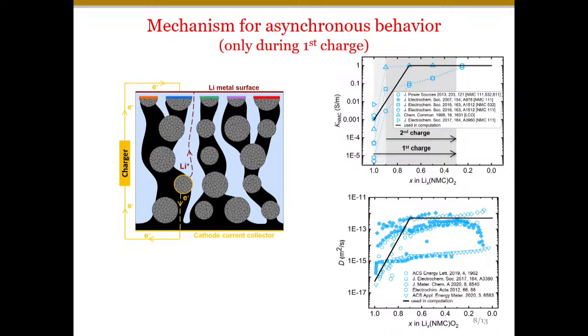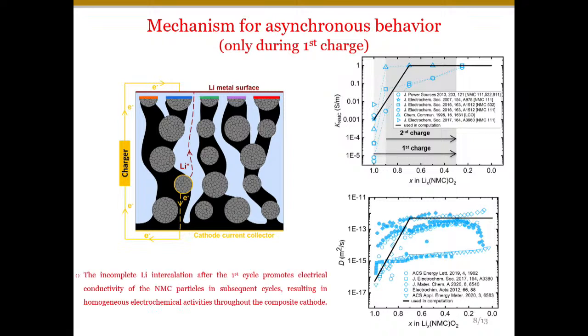So when you start the first charge, you are at a low value of electrical conductivity and diffusivity, but after that you are not able to achieve your pure pristine state, and you inherently start from higher values of both. So the asynchronous behavior diminishes.